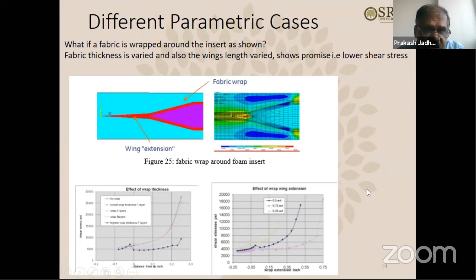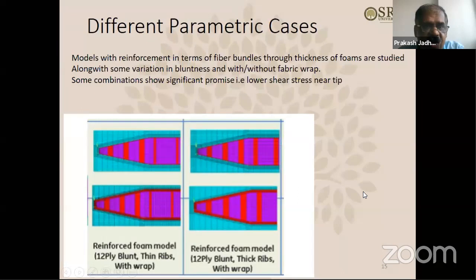And then we manufactured some of the coupons with these promising cases that I'll show you. Yeah. Okay, there was one more case that we tried. How about we insert vertical fibers inside the embedded foam insert, okay? So that this foam insert can become a little bit stronger. This also we tried, vertical fiber reinforced foam insert. So basically we have an embedded foam, but that foam will be reinforced with fibers. So if you try like this, what is going to happen? This also we tried, fiber bundles going through the thickness of the foam in vertical direction like this.